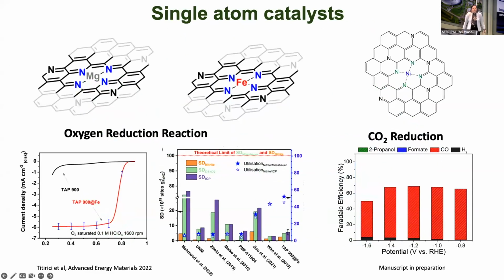But just to say that we work a lot on the design of single atom catalysts within carbon materials. So all of this can be derived from biomass. We've learned this process where we can do this magnesium templating, and we do some nitrogen doping, magnesium coordinates to these nitrogens, and then we can exchange the magnesium for different metals. In this case, it took us a long time, because when you make the single atom catalyst, you always get a mixture of phases, and it's quite difficult to get a single atom. But I think with this method, we can now be quite sure that we have the majority of sites as single atoms, so we can work a lot with iron as well as nickel.